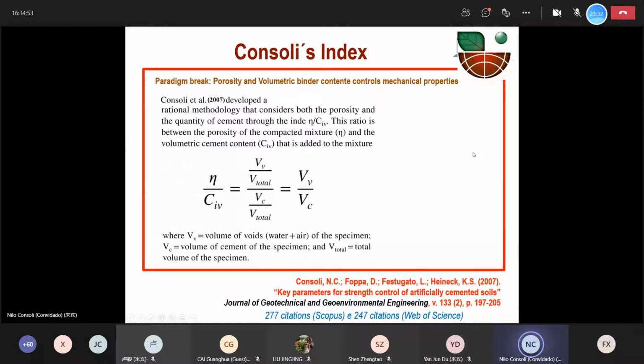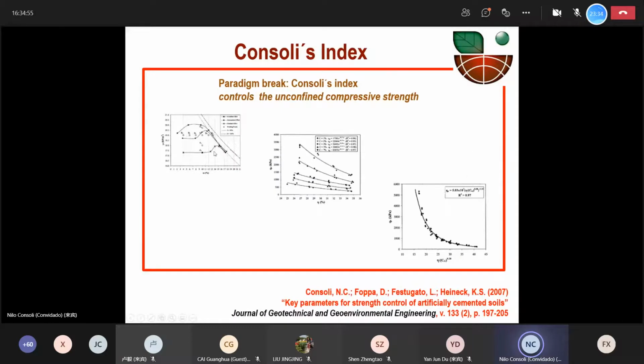So just to have an idea in this case, if we have some compaction curves with different energy, and if we choose some points of different dry unit weights and also some points with different moisture contents, so different dry densities, using different amounts of cement from 1 to 7%, we can get here a drawing porosity versus unconfined compressive strength for each amount of cement. These are the results for 1%, 2, 3, 5, and even 7%, each one with different porosities.